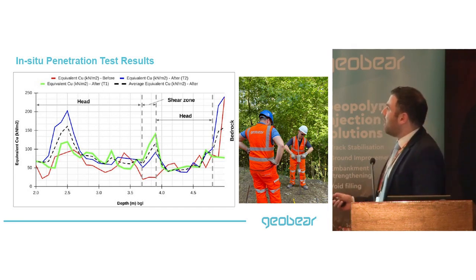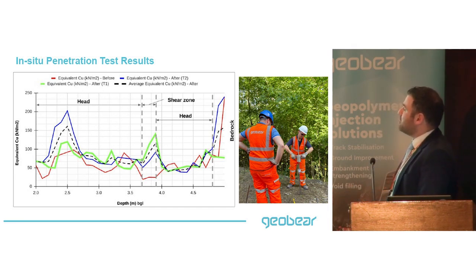If you compare what happened within the shear zone, the shear strength was around 25 kPa, and we managed to improve that all the way to around 120 kPa. As you can see, there's a significant jump in the shear zone because we specifically targeted that area surgically.